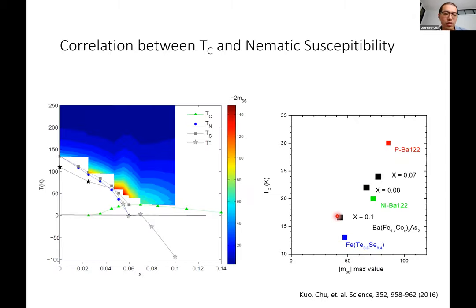And then you can measure that across a wide range of doping of these materials. If you plot this elasto-resistance coefficient in a color map, what you can see is that it has the strongest intensity near the optimal doping. And in fact, if you plot the superconducting Tc versus the maximum value of the elasto-resistance coefficient of a range of iron-based superconductors, including the phosphorus doped, the nickel doped, the iron chalcogenides, and a few cobalt doped, which are these black dots, you'll find that there's a nice linear correlation between the maximum of the nematic susceptibility and the Tc of the material.